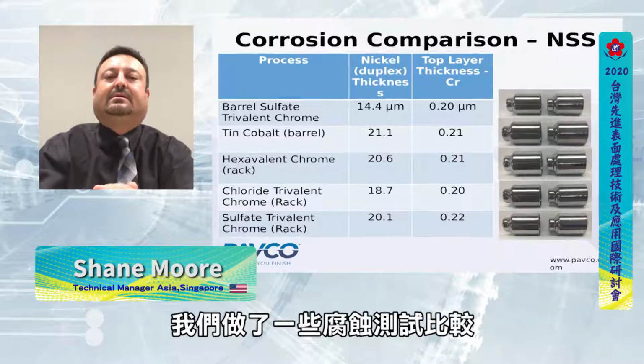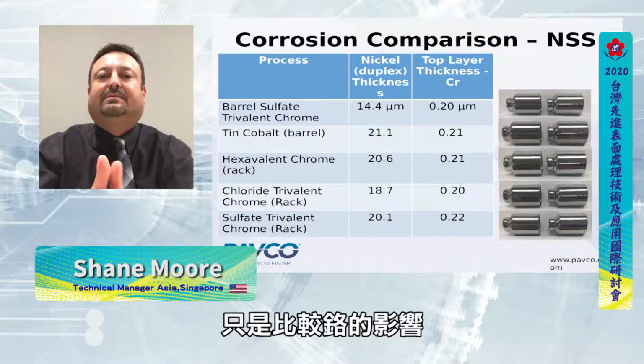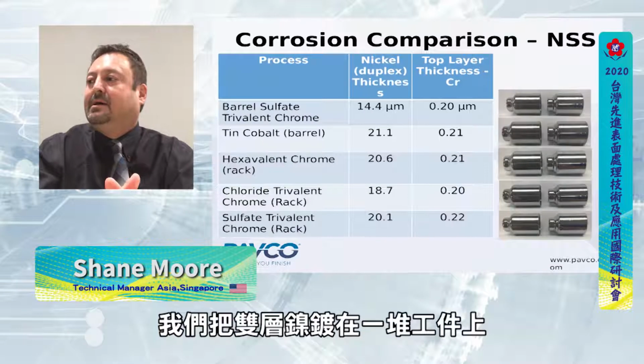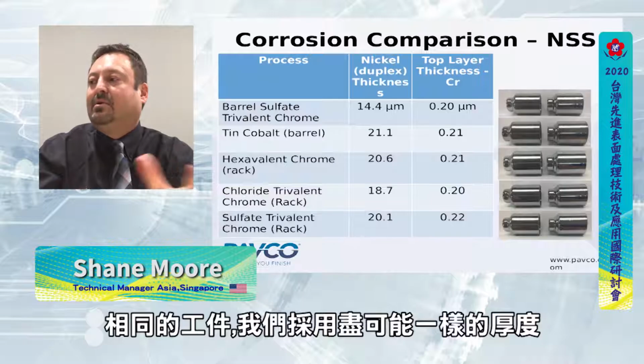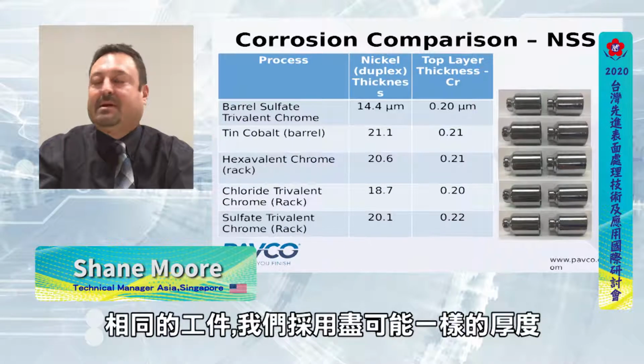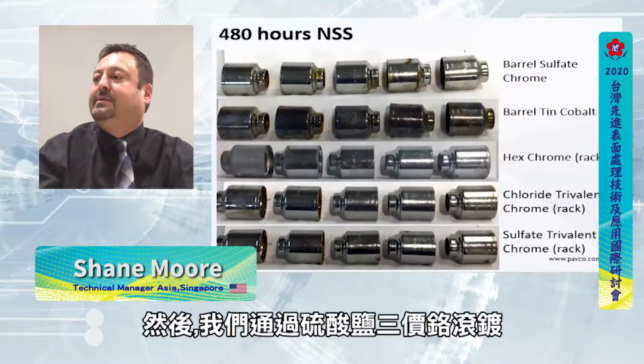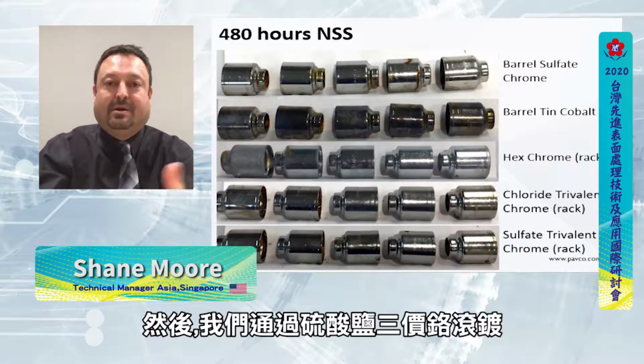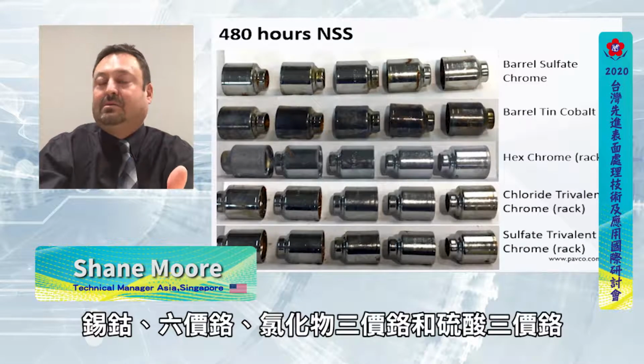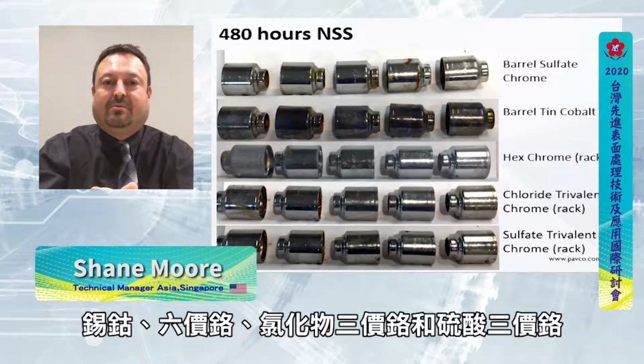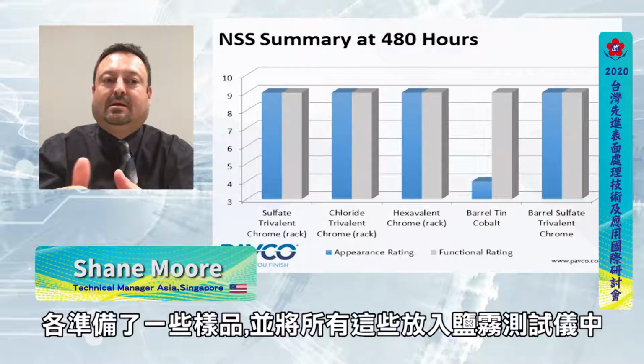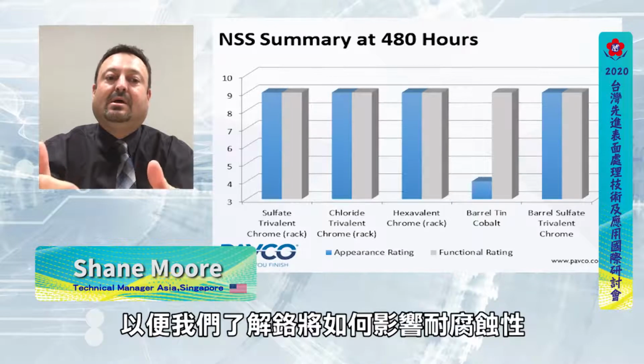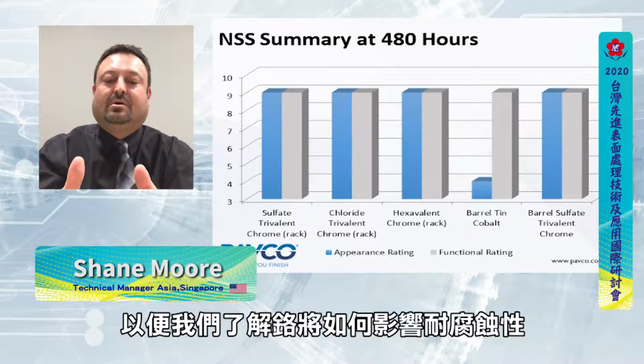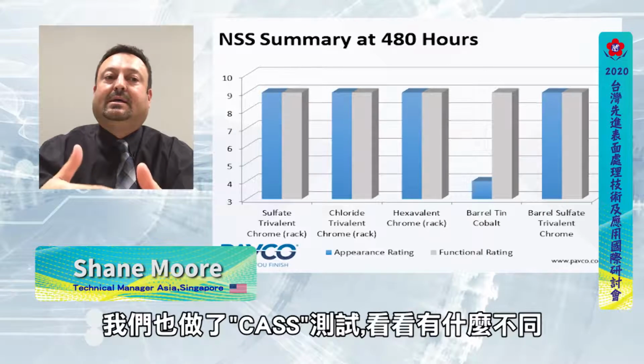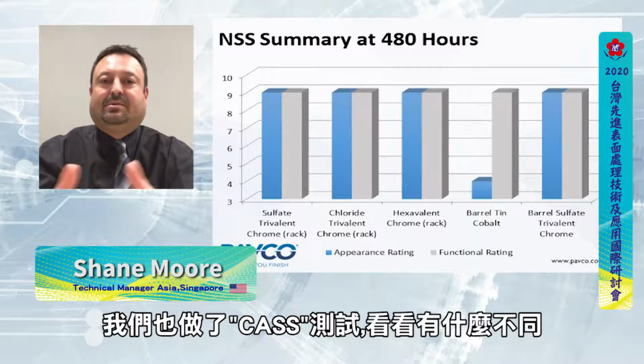So we did some corrosion comparing on just the effects of the chromium deposits. So what we did was we plated duplex nickel on a bunch of parts. They're all the same parts. We tried to get them as close in thickness as possible, which we did. It was around 20 microns total. And then we processed some through the barrel sulfate trivalent chrome, tin cobalt, the hexavalent chromium, chloride trivalent chromium, and the sulfate trivalent chromium. And we put all these in the neutral salt spray chamber just so we could see how just the chromium would affect the corrosion resistance. And we also did it with a CASS chamber just to see what the difference was there as well.